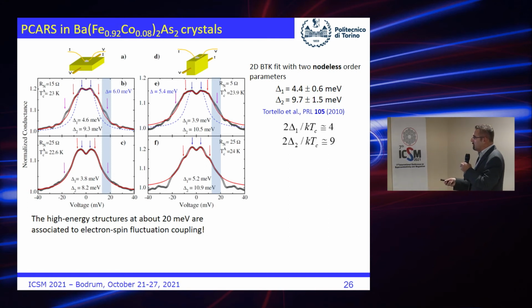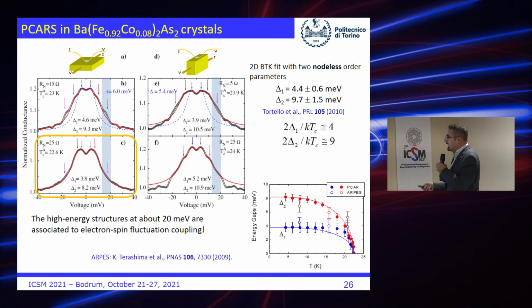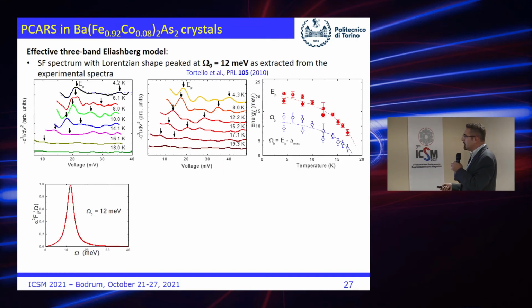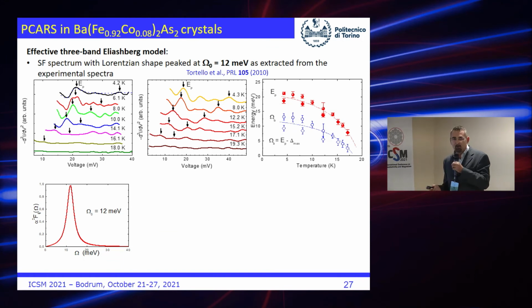The gaps I have are more or less this value, so 4.4 and 9.7. Again, there is a large uncertainty. We can calculate. By the way, this is the temperature dependence of the gaps extracted from this curve. Again, we can look at the problem by using the same approach, but the inverse.